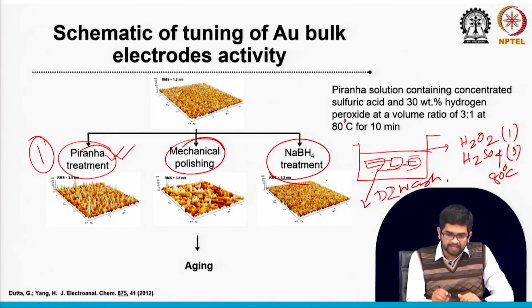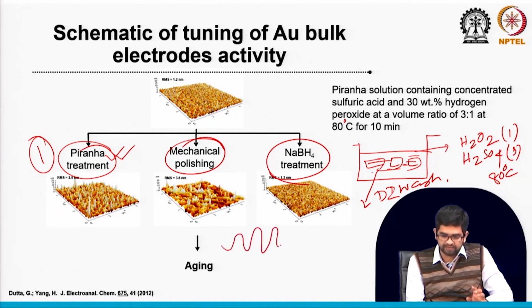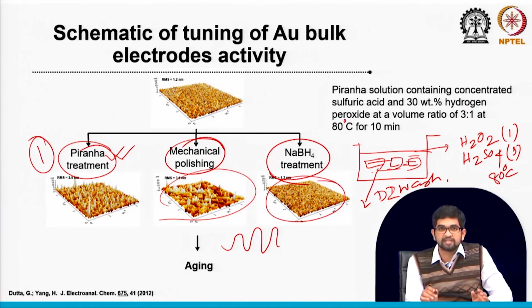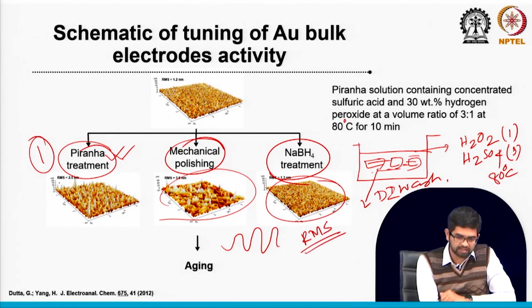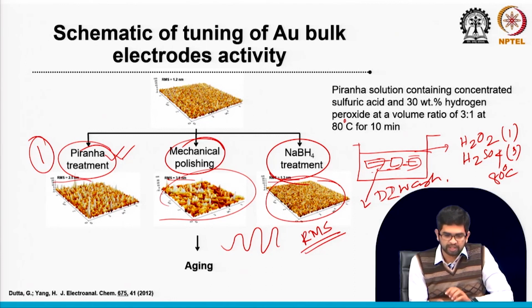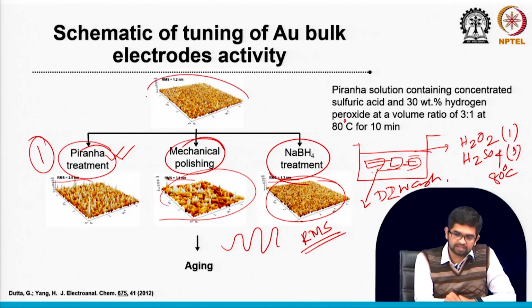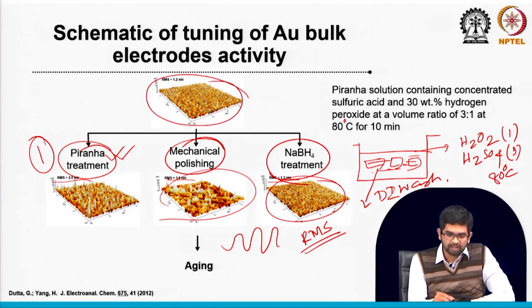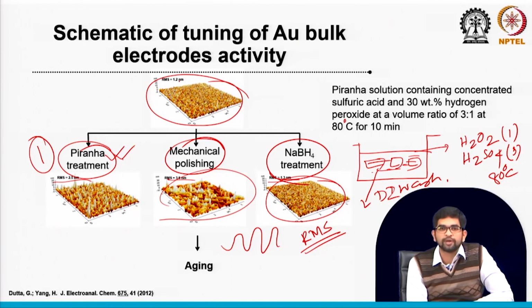See, in the mechanical polishing case, we have already seen that the surface roughness changes, right, hill and valley type, before and after the polishing. And the sodium borohydride treatment, you have already seen the surface roughness, that's called the RMS value, root mean square value. You can see here the RMS 2.5, 3.6, 1.3. So it's telling about the surface roughness. Especially in the sodium borohydride case, this is just before the treatment. Before the treatment, RMS value is 1.2 nanometer, and after the treatment it is almost similar.